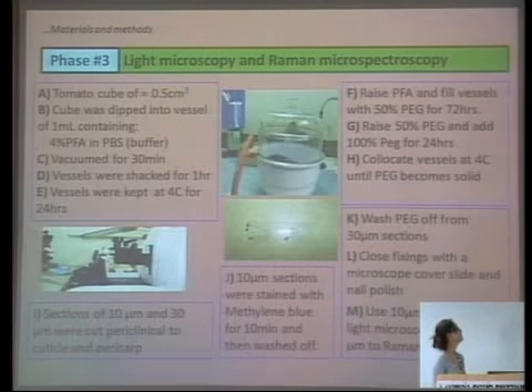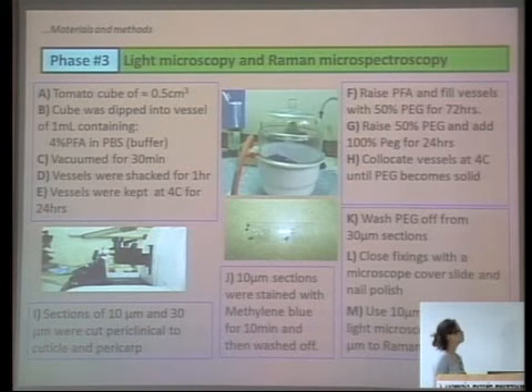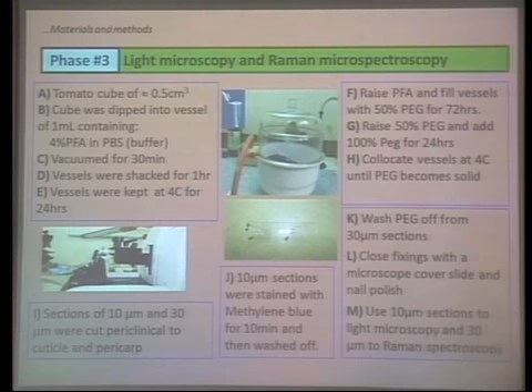What we did is we took a tomato cube of around 0.5 centimeters and put it into a solution of 4% paraformaldehyde in PBS, phosphate buffered saline. We applied vacuum for 30 minutes so the solution would get into the cells. Then we shook it for an hour, and then we put it at 4 degrees Celsius for 24 hours in the refrigerator.